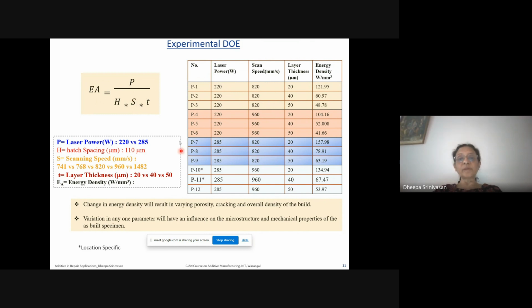So what we tried first was changing the laser power, scan speed, layer thickness, and thereby the energy density. As you know, the energy density is nothing but laser power divided by hatch spacing into scan speed into layer thickness. And we also did location specific variation, how the variation in the process parameter is going to have an influence on the microstructure and the mechanical properties of the as built specimen.